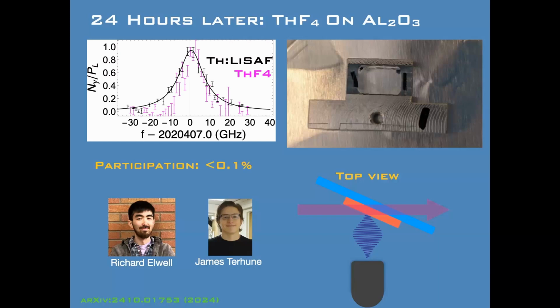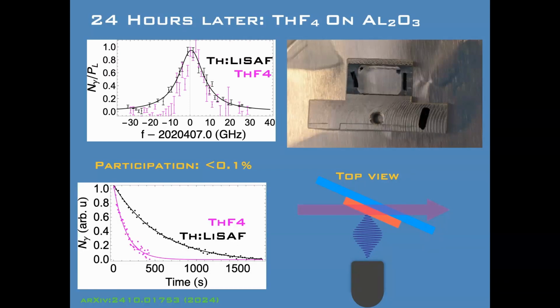One is, you see, this is very noisy. That's not because the experiment was worse, it's because the signal to noise is very low. And it shouldn't have been. The participation fraction here is less than 0.1%. So somehow a lot of nuclei are quenched in these films. And more interesting, and perhaps also related, their lifetime is about 4 times shorter in these films.